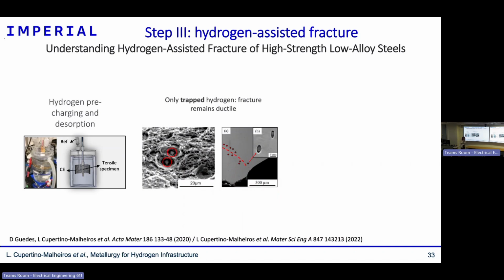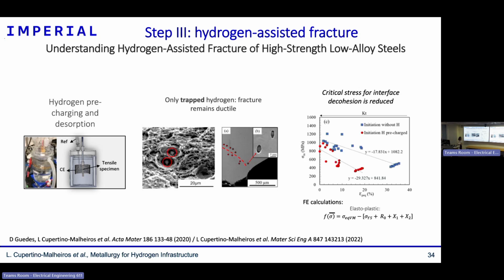So the first thing I do is look at the fracture surface under the microscope. In that case, we can see that the morphology of the fracture surface is full of voids, which is the characteristic fracture morphology of those steels when fracturing in air. That's a ductile morphology. And the second thing, I have done a cross-section to image those voids, those damage sites around particles, on this cross-section here. That is the second figure. And then I coupled those experimental results with some finite element elastoplastic simulations. What I could see is that hydrogen reduced the critical stress for decohesion around those particles. And that can justify why trapped hydrogen causes a certain level of embrittlement, even though the fracture surface, the fracture mode, didn't change and remained ductile.